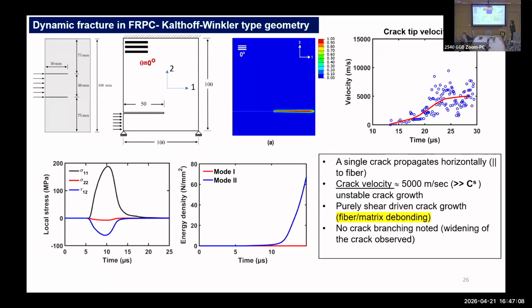We continue doing this, and this is a Kalthoff-Winkler type geometry. This is a classical example of dynamic fracture in isotropic material. Here, the idea is that you have a specimen with 2 notches on one side, and then you impact with, again, a compressive wave, a high velocity impact, in between these 2 notches. To exploit the symmetry, we just model half of it, and we consider different orientations of the fiber and see how the crack propagation changes.